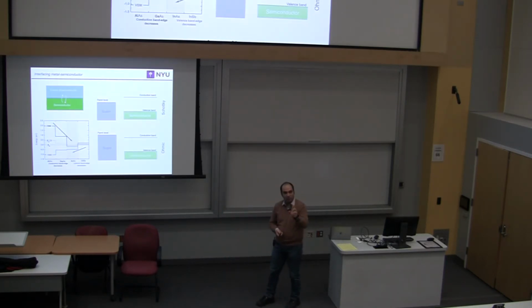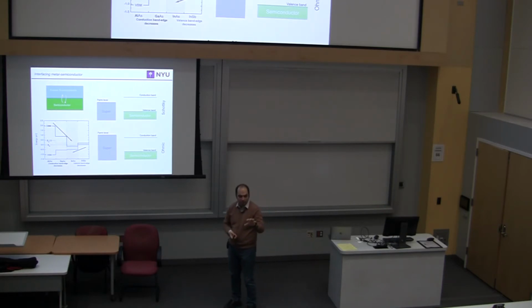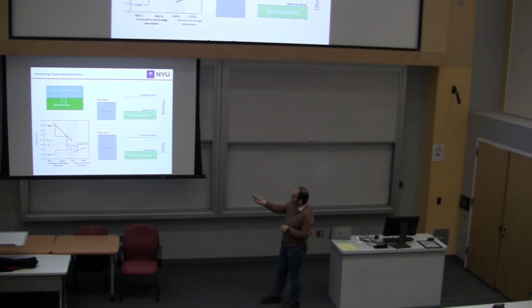Let me also tell you why 0.81 was an important number too. You know that in most materials like silicon, gallium arsenide, if you put a metal on top, the electrons are depleted from the surface and you get a Schottky barrier, right? That's a standard textbook thing. And that is true because the Fermi level at the surface of those materials is pinned in the band gap, right? So this is the band gap. The Fermi level at the surface is pinned in the band gap. Don't confuse bulk and surface. Surface is on this side. And indium arsenide is an exception because the Fermi level at the surface is above the conduction band of indium arsenide.